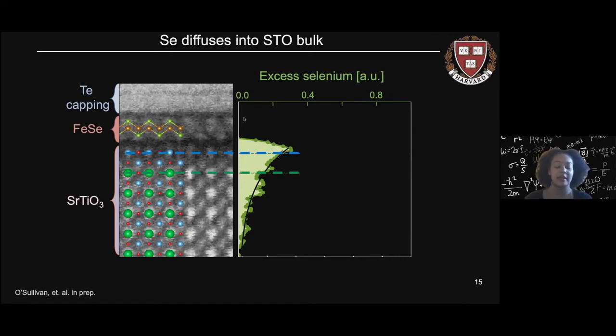Here we can quantify in arbitrary units the amount of excess selenium and specifically where it is located. So you'll note, as I previously mentioned, that excess selenium diffuses several unit cells deep into the strontium titanate bulk, well below the monolayer and well below even the top layer of titanium. This is strong evidence for selenium diffusion into the strontium titanate bulk.